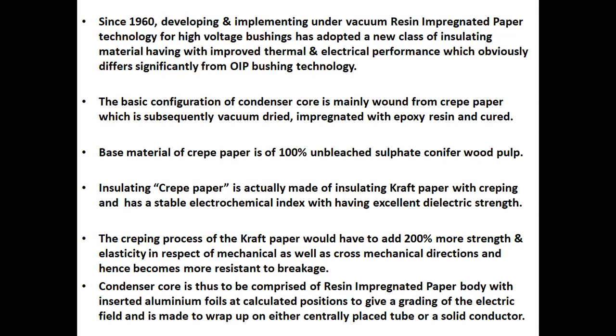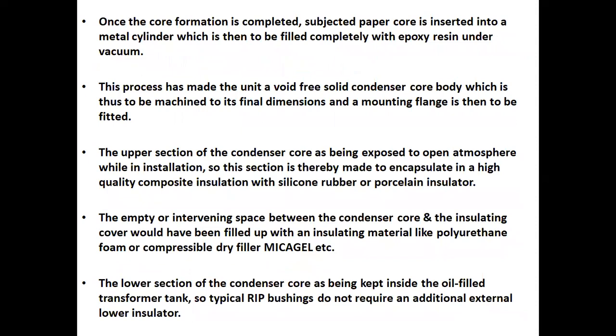The condenser core is thus comprised of a resin impregnated paper body with inserted aluminum foils at calculated positions to give a grading of the electric field, and is wrapped on either a centrally placed tube or solid conductor. Once the core formation is completed, the paper core is inserted into a metal cylinder, which is then filled completely with epoxy resin under vacuum.